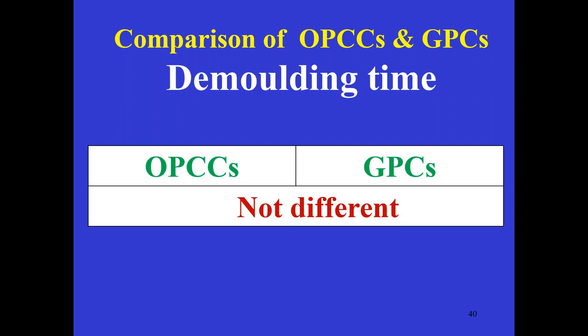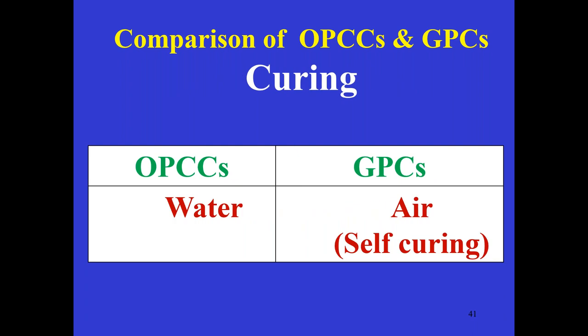Demolding time, actually no difference, but we can make it faster in geopolymer, but that is not a main issue here. So the demolding time can be planned as in OPC as well as in GPC. It is not different. Only thing that is important is curing. In geopolymer concrete, we should never use water because we are talking about polymerization. Polymerization does not require water for reaction, whereas in Portland cement, water is required for reaction. That's why we must do the water curing. Without water or moisture, there is no curing and there is no strength development, and OPC concrete is very bad. It will deteriorate. Whereas geopolymer, if you put water, it will deteriorate. Only air curing and self-curing. Sometimes you may use hot curing also, hot air curing. That means this curing is so different here. That's the only difference.